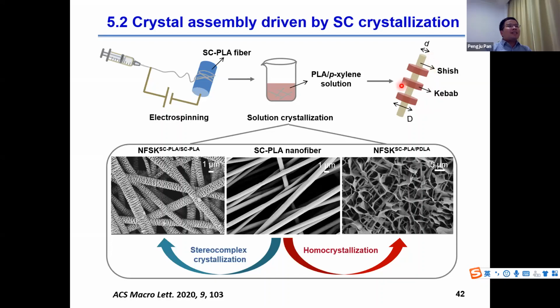In this study, we prepare the fiber by electrospinning, and use this electrospun fiber as the shish. Then we dip the fiber in the solution of PLA or PDLA homopolymer or the PLA PDLA mixture to grow the kebab crystal on the surface of the fiber. In both cases, we can obtain the shish-kebab crystal. But the crystal morphologies are very different in these two cases.